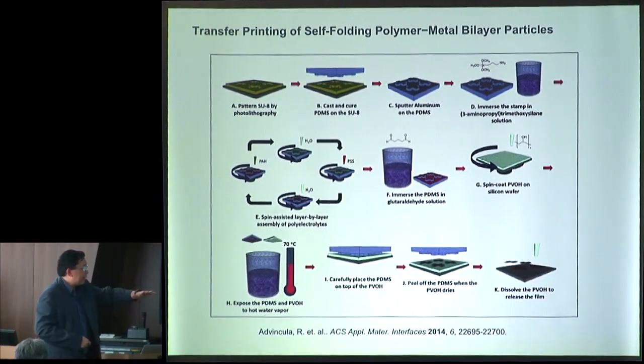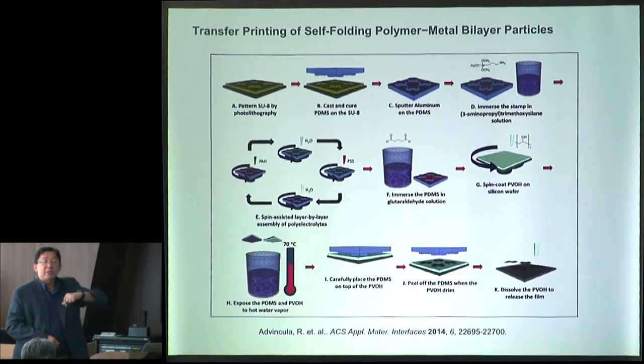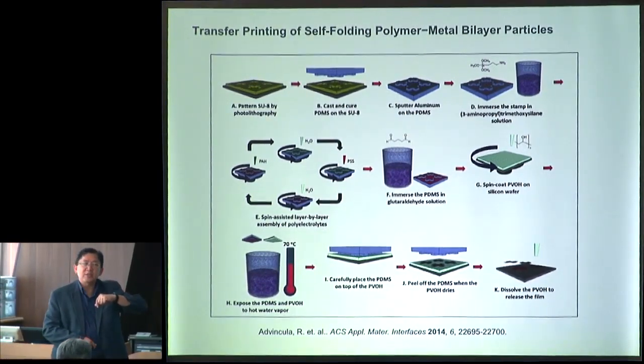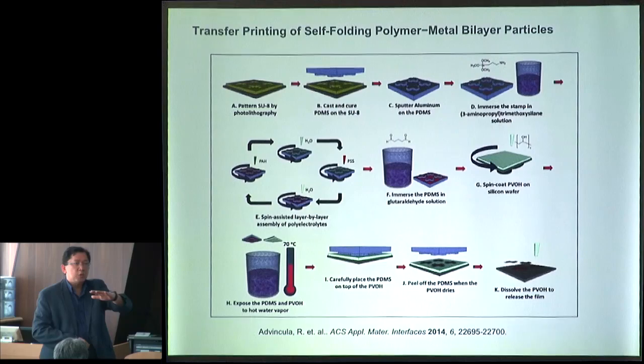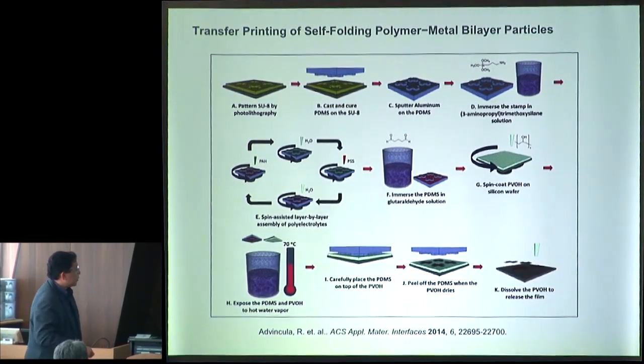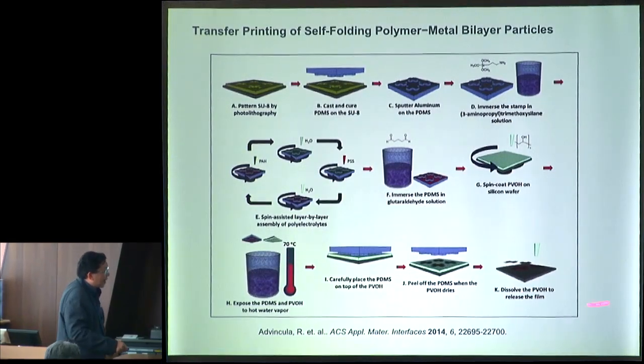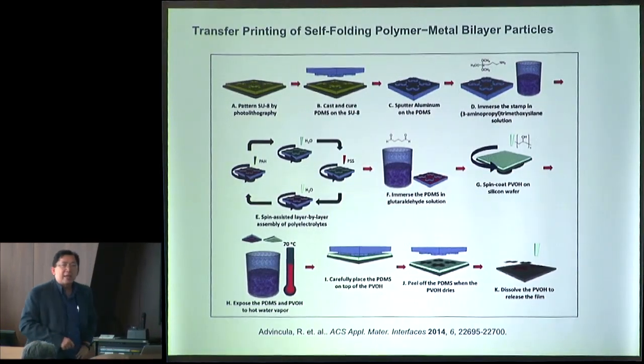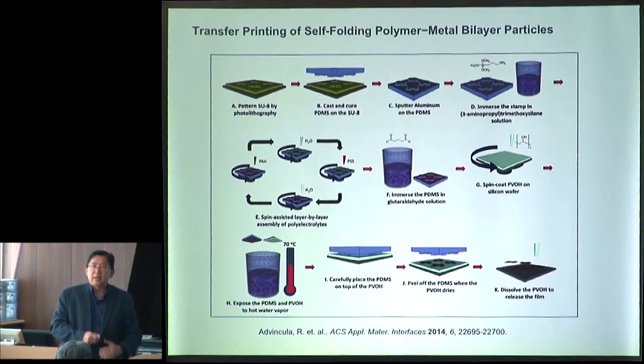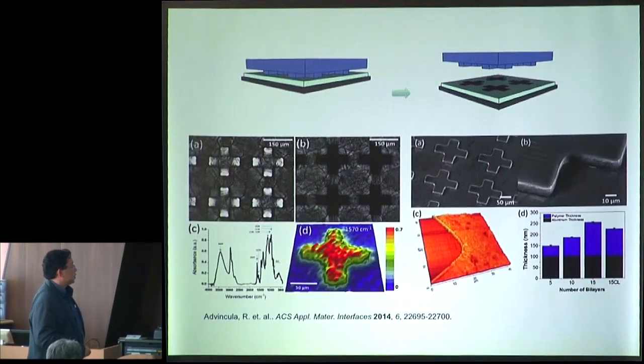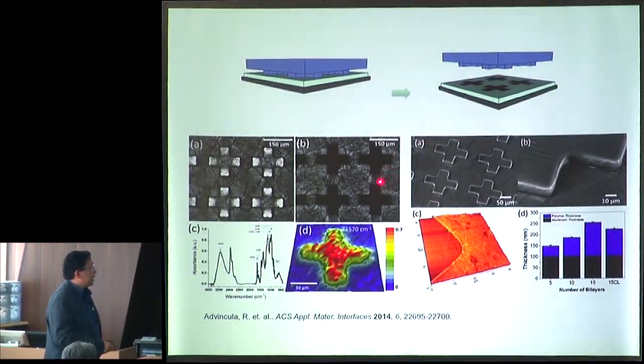The soft layer would be your polyelectrolyte layer by layer, and then this was put on top of a sacrificial polyvinyl alcohol layer, such that when we put it in water, it will dissolve the PVOH and then lift up the particle. So in other words, what we wanted to do is achieve particles that can be observed to fold under microscopic conditions. Here you can see the fidelity of the pattern.